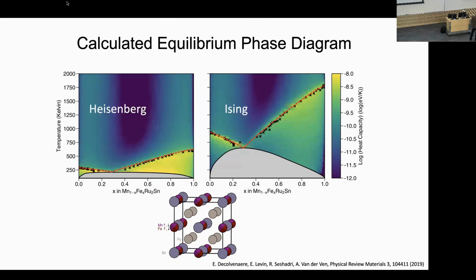So this sublattice you can mix with manganese and iron, and so you can vary the composition of this Heusler phase. If you start with the manganese over here, and then replace manganese with iron, you can make it more and more iron rich. And this is the calculated phase diagram. So this is a temperature axis, composition axis. And it shows a miscibility gap and also magnetic transitions.